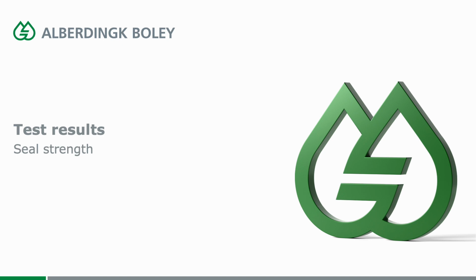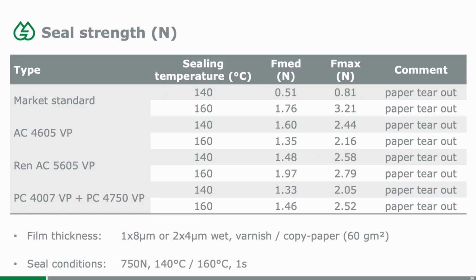Another important question then, if we think about making packagings, is can you seal these products? What is the seal strength? And here we are measuring the seal strength on the copy paper. So it's probably not the best substrate to do it because it's a very, very lightweight paper. We are also using a slightly not ideal equipment. We have a Brugger heat seal machine, which is traditionally used for foil heat seal testing, so paper might not be the ideal material in this machine, and we are sealing varnish versus paper.